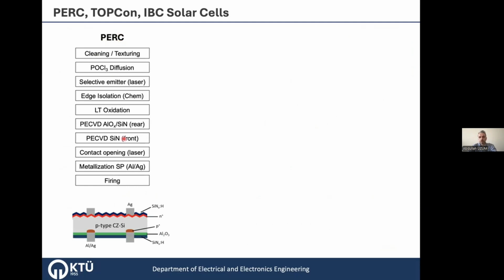If we look at this schematic here, you see that the backside of this solar cell is different from the full BSF solar cell. In the back surface field solar cell, we had a P plus layer all over the back surface and aluminum all over the back surface. What we try to do with the PERC structure is local contacts to decrease the recombination, and a passivated rear layer here to decrease the recombination, and that will also increase the light trapping. It will reflect light back and increase the absorbance.